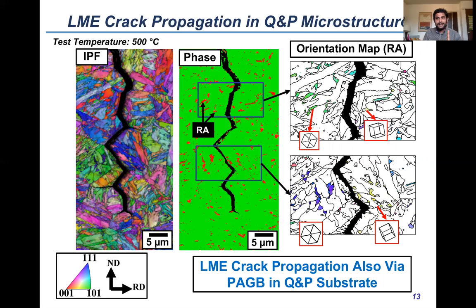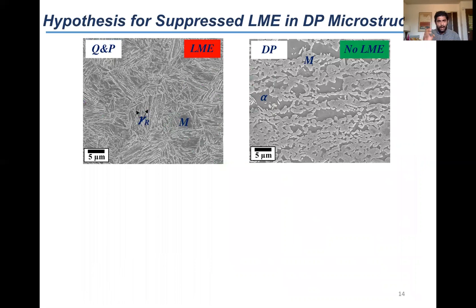So the prior austenite boundaries were responsible for LME cracking in the martensitic, Q&P and also in the TBF, which I'm not showing over here, but we have also analyzed. All these microstructures cracked because of the presence of prior austenite boundaries. Now, what happened with the DP microstructure? So here is a hypothesis for why the LME was suppressed in the DP microstructure. I call it a hypothesis because I really do not know why the prior austenite boundaries are prone to cracking.